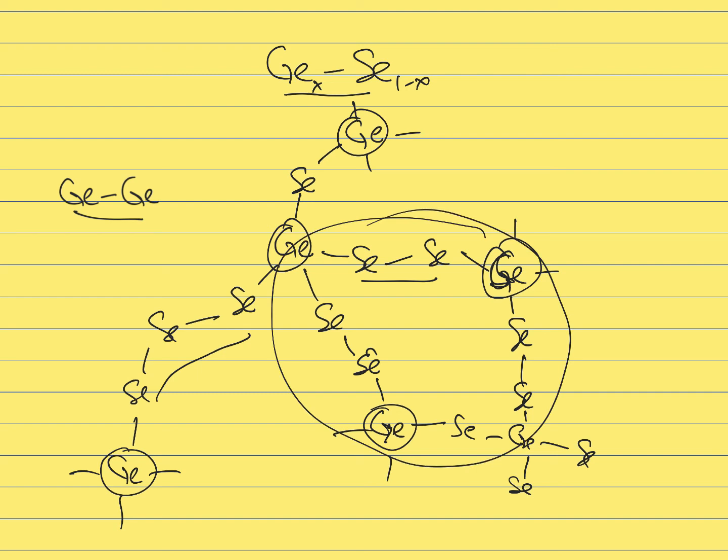And in the case of chalcogenide glasses, unlike oxide glasses, you don't always have a selenium in between two germanium, or a germanium in between two selenium. So when it comes to chalcogenide glasses, we define the ring size, the size of the rings that are formed, where the rings are some closed path like this in the structure, where you start from one atom and you form a closed path to come back to the same atom. In this case, the size of the ring will be just given by how many atoms these rings comprise. So in this case, that would be an example of 1, 2, 3, 4, 5, 6, 7, 8, 9, 10, 11. That would be an 11-membered ring in this case. You count all the atoms to count the size of the ring.